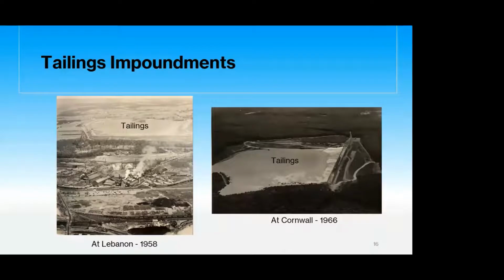After the tailings were reprocessed, they were disposed of in large tailings impoundments that were located close to the concentrator plant in Lebanon on the north side of Route 72 near the intersection of Maple Street and Jonestown Road in an area referred to as Sand Hill. You can see this large impoundment above the concentrator plant in the photo on the left. After the concentrator relocated to Cornwall in 1962, the millers stopped reprocessing the tailings and sent them directly to a large tailings impoundment located in Cornwall above Rexmont. This tailings impoundment is shown on the photo on the right. Today, you can view the embankment for this tailings impoundment as you're driving on Route 419 just east of Cornwall, but keep your eyes on the road, please.